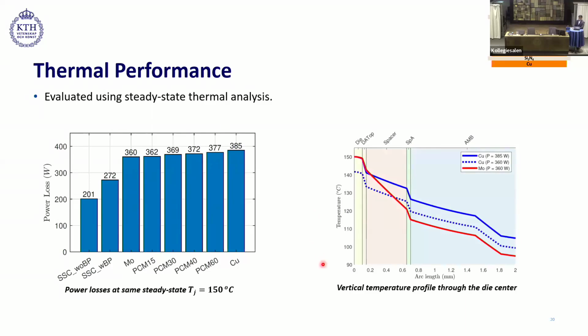Again, looking at the vertical temperature profile through the Ag-sinter, we see that molybdenum exhibited higher temperature drop across it than copper. And that's again because molybdenum has 3 times higher thermal resistance than copper.